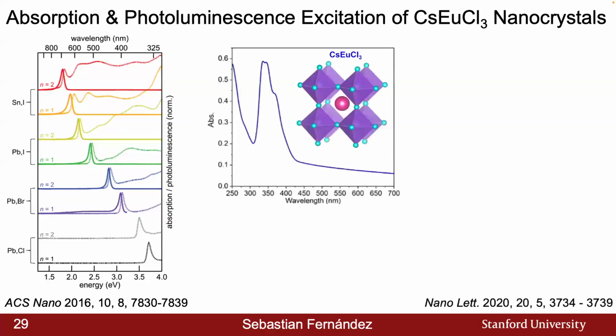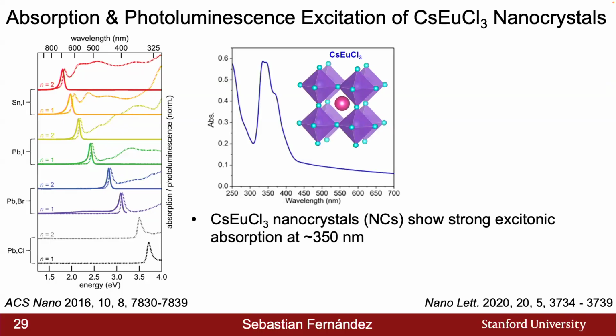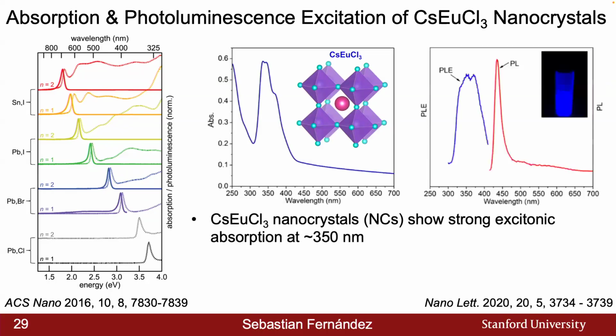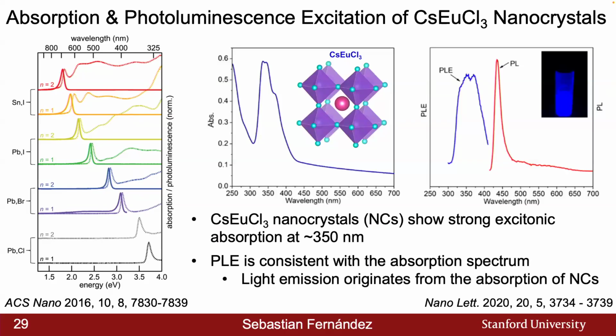But we can go no farther than actually UC Berkeley within Peidong Yang's group and see that they've created cesium europium chloride-based nanocrystals that have this strong excitonic absorption around 350 nanometers. However, their nanocrystals in this case emit at around 435 nanometers. But because there's really good adherence between the photoluminescence excitation and the absorption spectrum here, the light emission is confirmed to be originating from the absorption of these nanocrystals, no matter how far the various absorption peak and the photoluminescence peak might be.